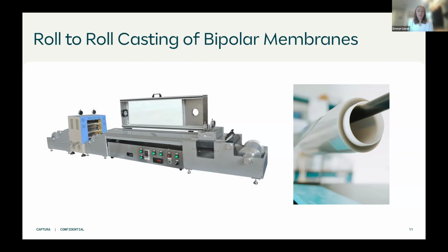For the bipolar membrane, we're able to then repeat this 3 times for each layer of the membrane. And really perfecting each of these steps has been a really critical aspect in the development of our membranes, and it is not a simple task to move from layering membranes and hand casting membranes to be able to directly roll-to-roll cast. And so this has been a really big and exciting step that we're now able to produce our membranes in this way after great trial and error.